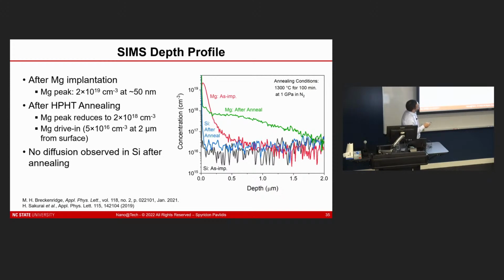But when you do this high pressure annealing, for the temperatures and the time that we're doing it, the magnesium actually redistributes. It diffuses through the material. And so this is quite interesting because I mentioned earlier that wide bandgap semiconductors don't typically have diffusion. We don't typically think about diffusion of these impurities, but for GaN, and especially in the case of magnesium, that's very different from silicon, that magnesium will move on you quite a bit. So you have to think a lot about that when you design your devices.